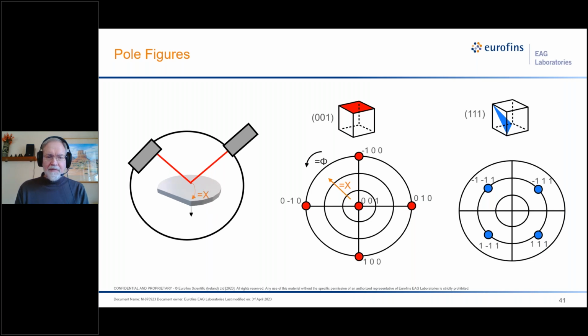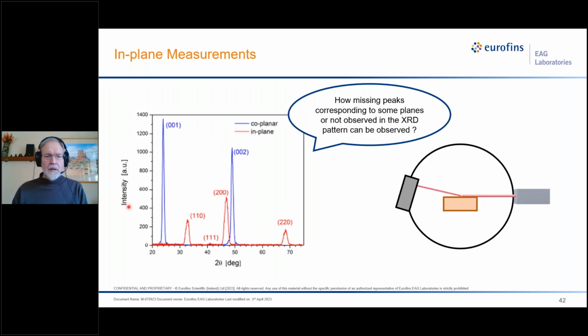So if you have something like a cubic phase like these two, you might have fiber texture where the 100 peak is at the center, and then there's basically no intensity until you're at 90 degrees. Whereas if you were looking at a pole figure for another plane, a 111 plane, you would not see any intensity until you get out to an angle in chi that's equal to the interplanar angle between the 001 and the 111. So from putting several of these pole figures together, you can get a three-dimensional picture for how the grains are textured in your sample. Back to you, Stephanie.